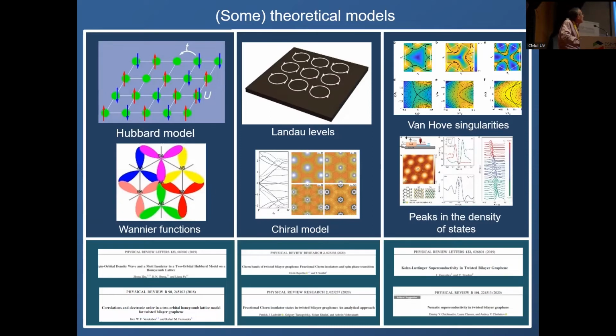You can think of it as some kind of Hubbard model, which is the traditional analysis made for strongly correlated systems. You can think of twisted bilayer graphene as a set of Landau levels, which is what you do when you study electrons in high magnetic fields. And you can notice that there are peaks in the density of states, and in two dimensions those are known as the Van Hove singularities, and you use those Van Hove singularities to guide your theoretical analysis.